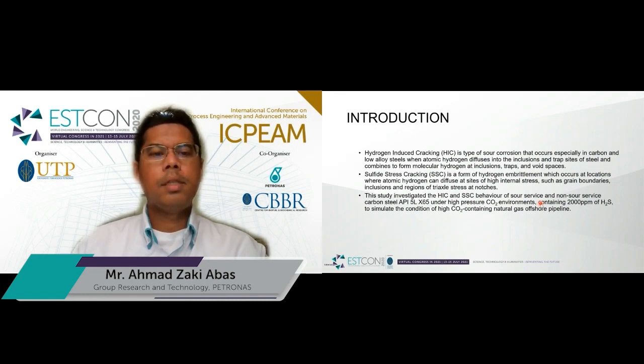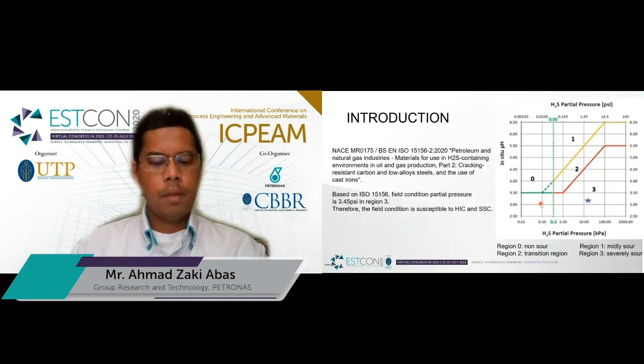This study investigates the hydrogen-induced cracking and sulfide stress cracking behavior of sour service and non-sour service carbon steel, which is API 5L X65, under a high pressure CO2 environment containing 2000 ppm H2S to simulate the condition of a high CO2 containing natural gas offshore pipeline.